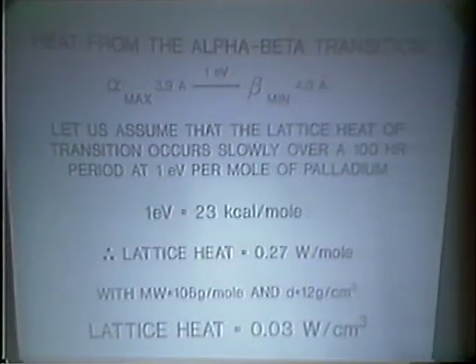Well, now the next one is to assume that, this is rather an odd one, perhaps you think it's unjustified, but to assume that the alpha to beta transition of palladium somehow wasn't complete, and that's been going on all the time, and that it's been going on all the time the electrolysis is going on. Could that be a source of the heat? I think most of you will think this is a fairly far out one and rather unlikely, and indeed it may be, but it doesn't really matter because, as you see, if you assume it's going on over 100 hours, I've carelessly just assumed it was 1 eV because I couldn't find a value for it. It's obviously of that order of magnitude. If it's 3 eV or 0.3 eV, it doesn't really make any difference because it gives an absolutely negligible contribution to 10 watts per cc.